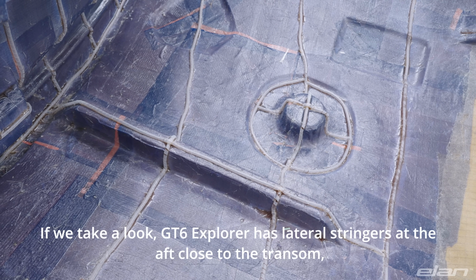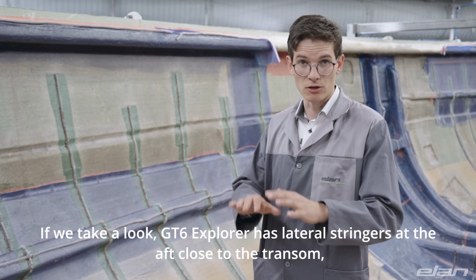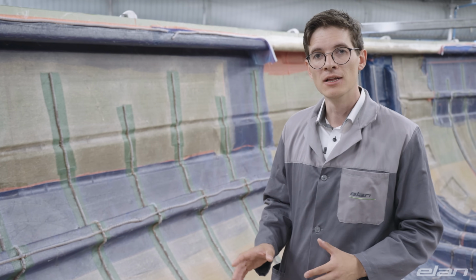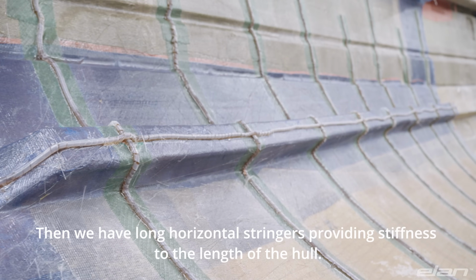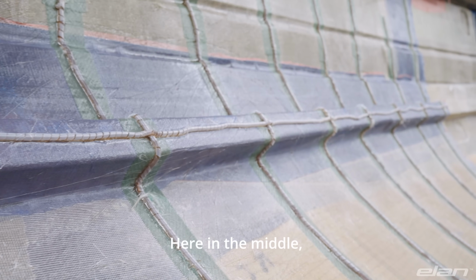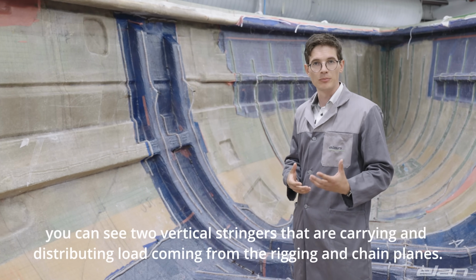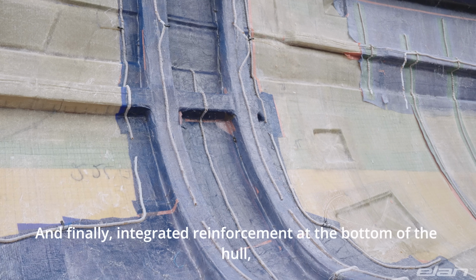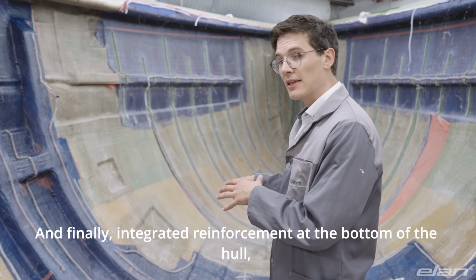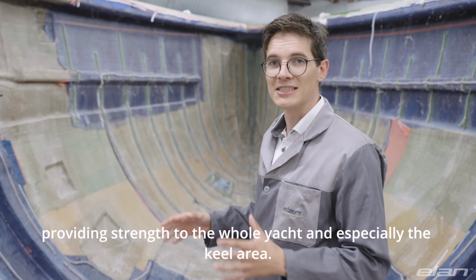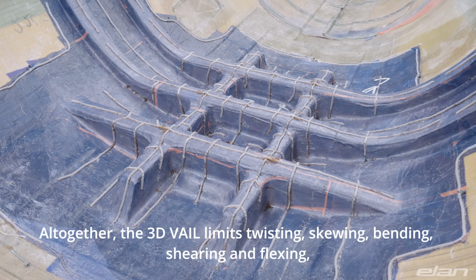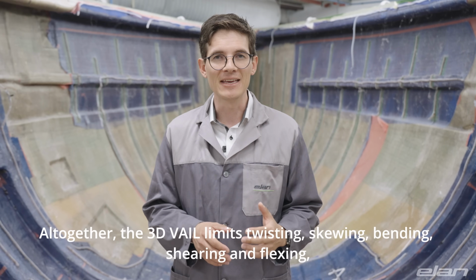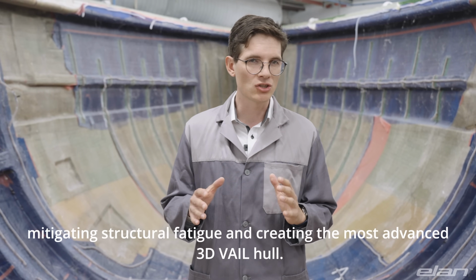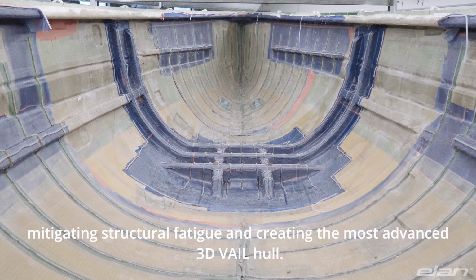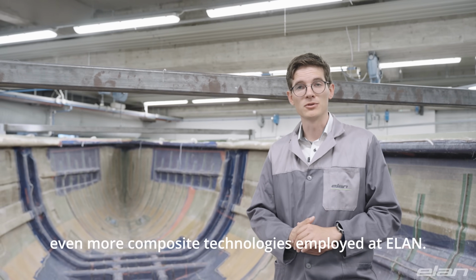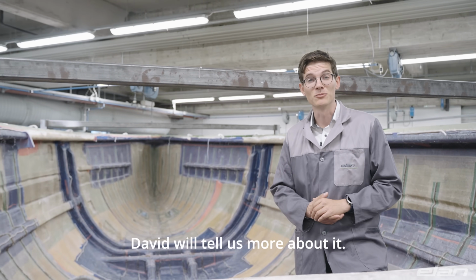If we take a look, GT6 Explorer has lateral stringers at the aft, close to the transom, providing stiffness to that part of the area. Then we have long horizontal stringers providing stiffness to the length of the hull. Here in the middle, you can see two vertical stringers that are carrying and distributing load coming from the rigging and chain plates. And finally, integrated reinforcement at the bottom of the hull, providing strength to the whole yacht and especially the keel area. Altogether, the 3D VAIL limits twisting, skewing, bending, shearing, and flexing, mitigating structural fatigue and creating the most advanced 3D VAIL hull. There are, however, even more composite technologies employed at Elan. David will tell us more about it.